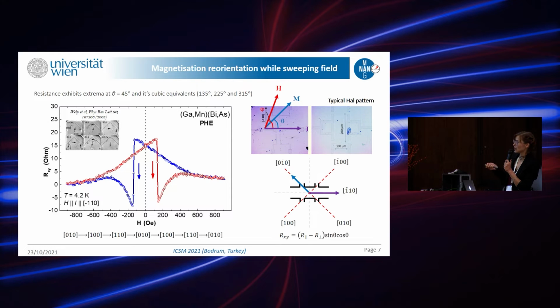Also, I would like to point your attention that the graph is very nice and symmetric, and the reorientation runs throughout the whole easy axis, because it's easy in-plane magnetization. We start with 0, minus 1, 0, and we go through the whole 360 degrees and come back to 0, minus 1, 0 at this point in the field. At 550 Oersted, in this case, we also have something which we coined a recurrence point, below which these effects of reorientation are suppressed by a strong enough field. So we have a negative magnetoresistance.